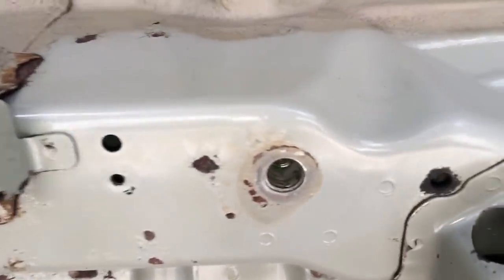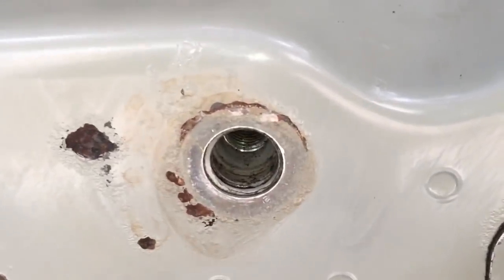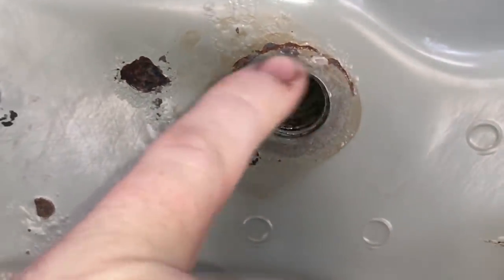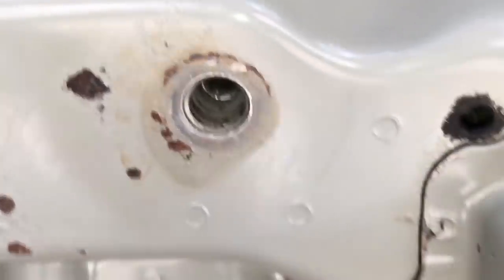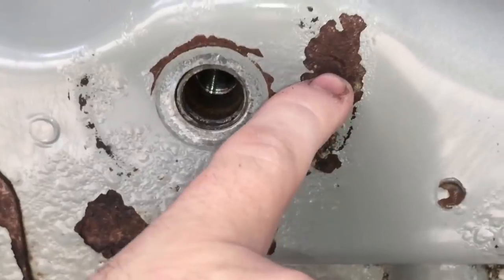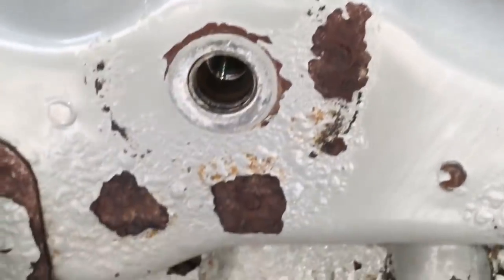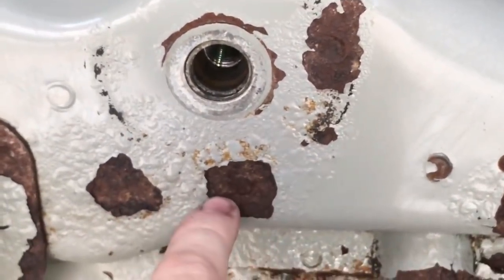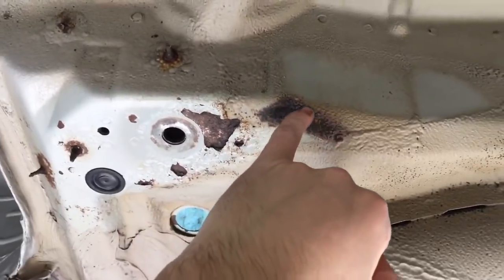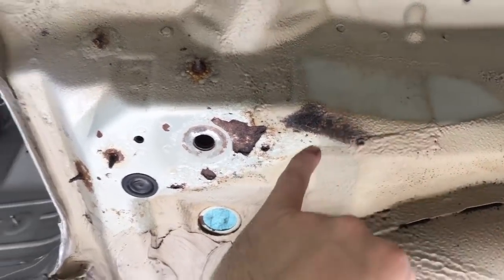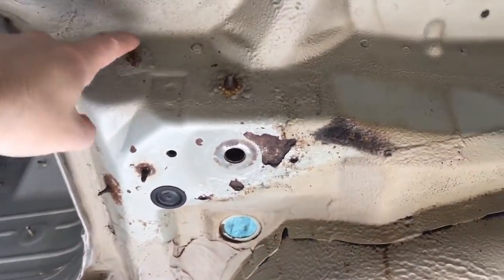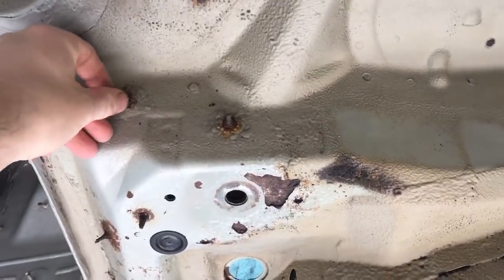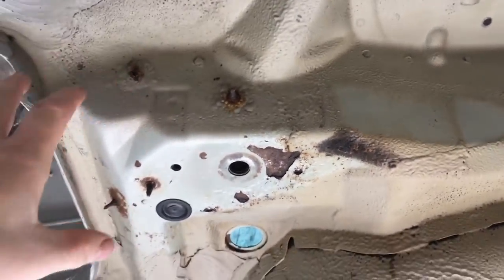So left front mounting point, definitely got signs of a hairline crack going around the middle of that mounting point, plus a spot weld flex there. A crack coming out of that spot weld going across that way with a hairline around there, a couple of badly flexed, possibly even a broken one there, spot welds that is. Right rear, always hard to find this one, so we've applied a little bit of heat and we've got a crack appearing just in the corner, so we need to deal with that and check on these spot welds, see whether they are just flex and corrosion or whether they are broken underneath.